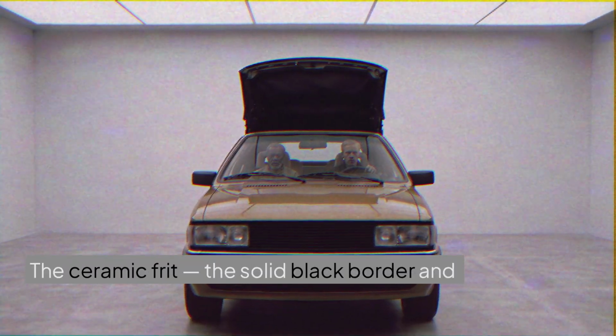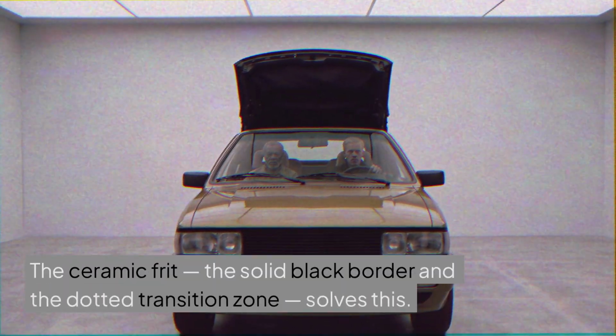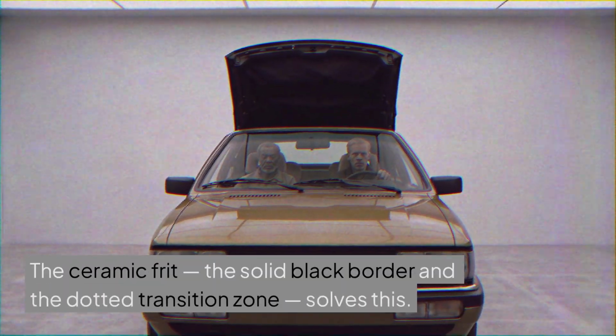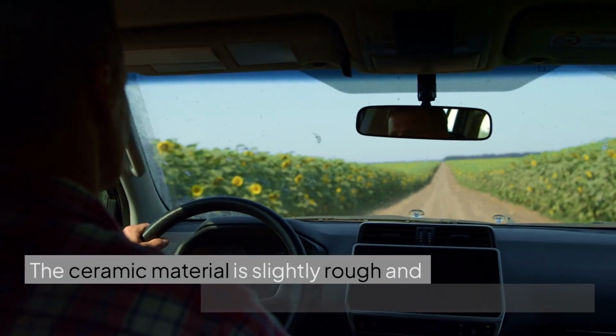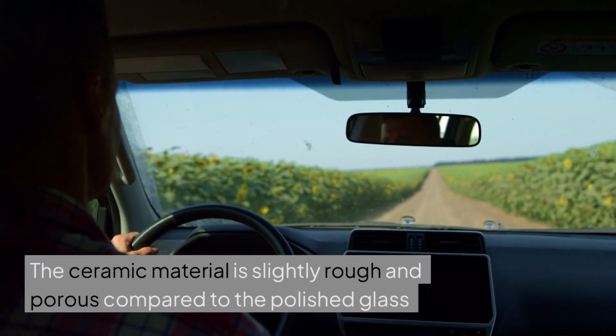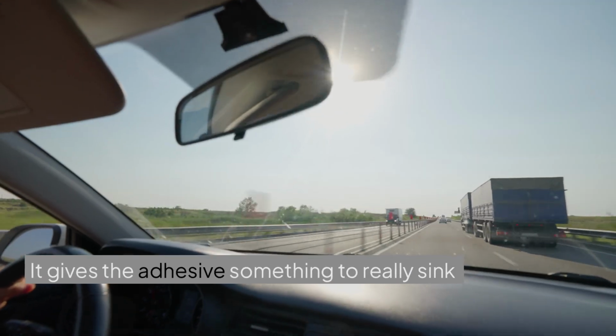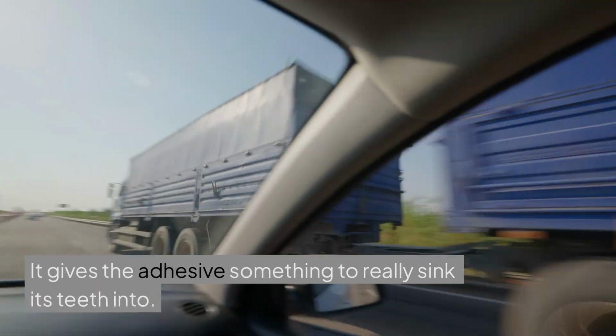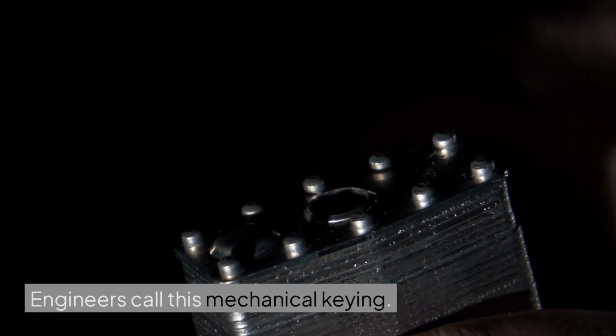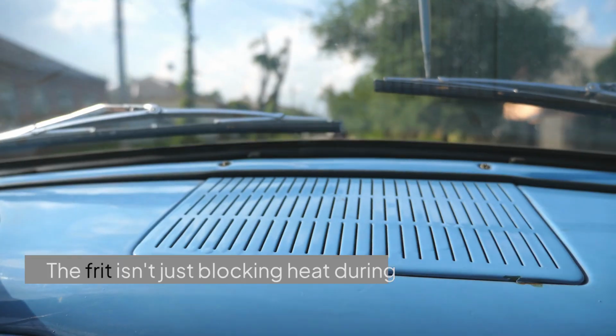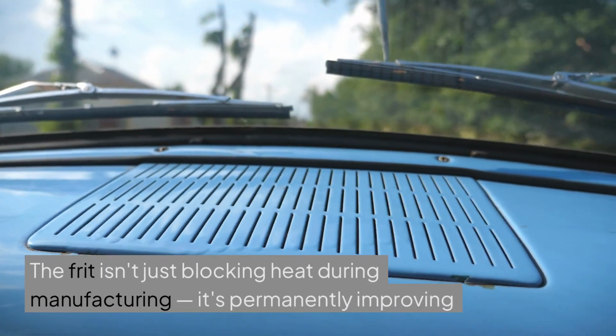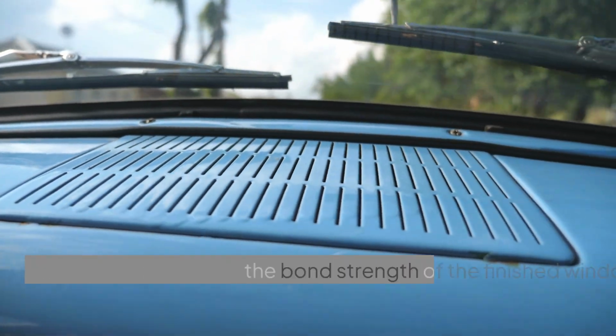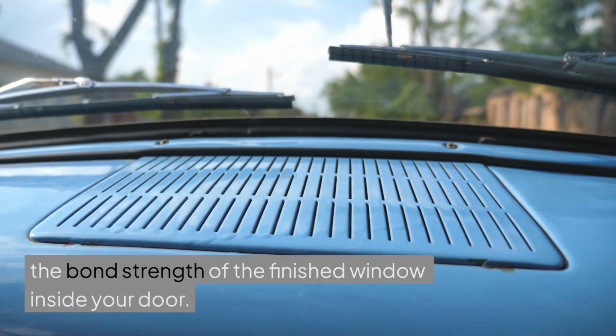The ceramic frit, the solid black border and the dotted transition zone, solves this. The ceramic material is slightly rough and porous compared to the polished glass surface. It gives the adhesive something to really sink its teeth into. Engineers call this mechanical keying. The frit isn't just blocking heat during manufacturing. It's permanently improving the bond strength of the finished window inside your door.